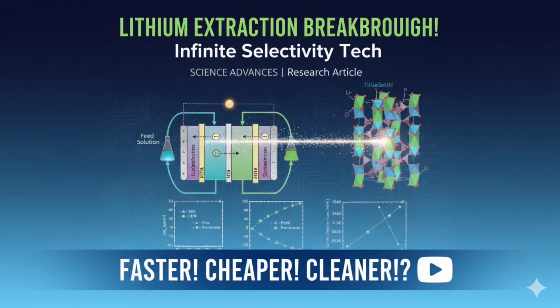Managing pH seems quite critical. Okay, so surface blocking from competitors and potential competition from protons inside the membrane. These are engineering challenges to address, but the core selectivity is still there. Absolutely. The core mechanism is sound, but optimizing the interface and managing the feed water chemistry, especially pH, will be key for real-world application. Got it.